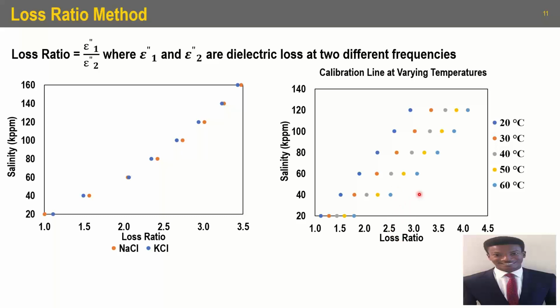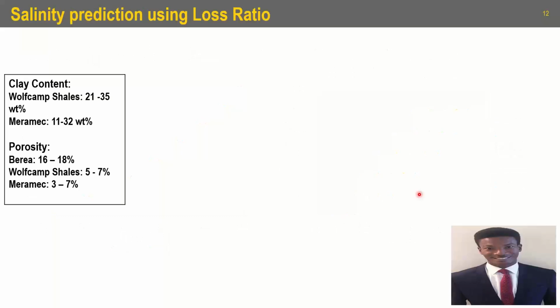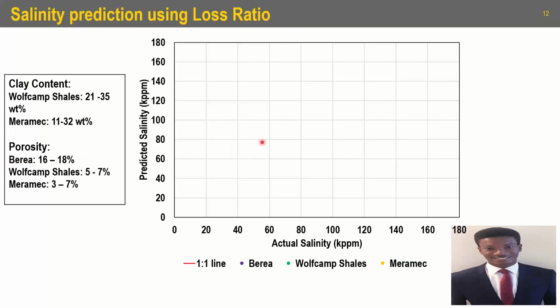So based on this, we then went ahead to use this developed methodology on different samples that had been saturated in brine of known concentrations for about 6 months. And these samples go across a wide clay content range from 11% to as high as 35%, and a porosity range from as low as 3% to as high as 18% for the various samples. On this chart, we see the predicted salinity compared with the actual salinity. The predicted salinity is what we get from our loss ratio measurements, and the actual salinity is the salinity of the brine concentration that we saturated our samples with.